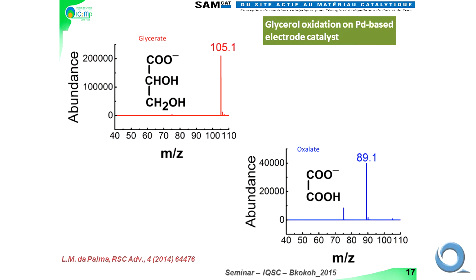And now we try to combine with NMR. The problem is you have traces of water, and you have some ppm of water inside your NMR spectrum. So we wanted to improve. And with this system, by mass spectroscopy, we have, for example, for the first time, the mass of the main reaction products, glycerate and oxalate. So by this way, we can improve the system.